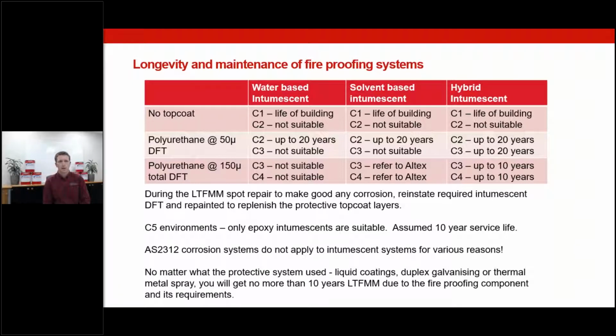There are certain Australian standards that give you guidance with regards to those timelines, which I can refer to later. But generally speaking, with a 25-year life to first major maintenance on, say, an exterior exposed bit of fireproofed steelwork, you're expected to make a spot repair to make good any corrosion issues, reinstate any required intumescent dry film thickness which would have been revealed from that corrosion, and repaint to replenish the protective top coat layers. With regards to fully exterior, in your lower right-hand column, C3, C4 environments, up to 10 years, that 10-year period is specifically for your polyurethane films that are protecting your intumescent coating system from the UV and the weather. It's those systems that need to be topped up every 10 years or so.